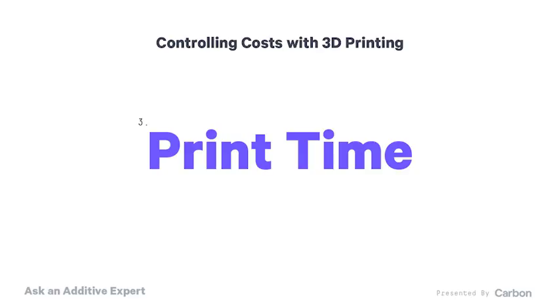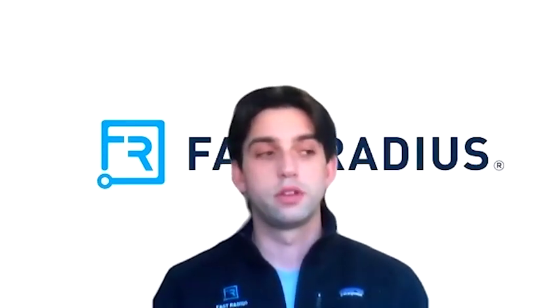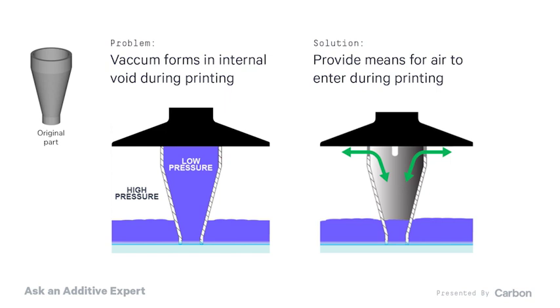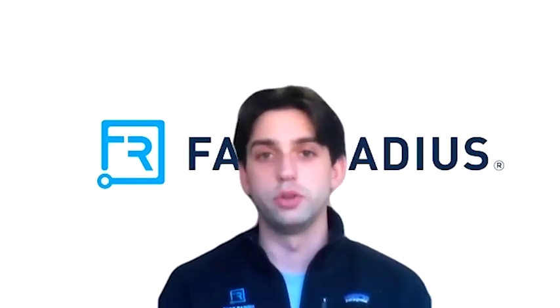Let's talk about the actual printing and post-processing itself, because this is another component of cost — the amount of time your parts are spending in the 3D printer. What are the considerations designers should think about? As you're getting trained on the Carbon technology, you've got to learn new design rules. One that's very important for Carbon is trapped volumes and trapped resin inside the part. The machine can recognize when there are certain layers that have a vacuum forming and will actually slow down. So when designing parts, we try to reduce the time on the printer by removing any and all trapped volumes or vacuum forming issues in the design.